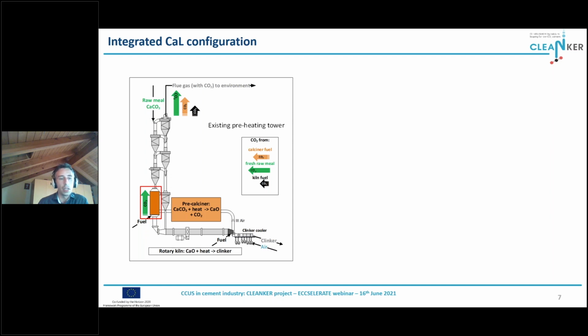First of all, we have the CO2 which can be named process CO2 emission, because it is related to the calcination of the material. So it doesn't come from combustion, but from the process itself. And this is almost entirely generated in the calciner of the cement kiln, which is the most energy intensive section of the whole cement production process.